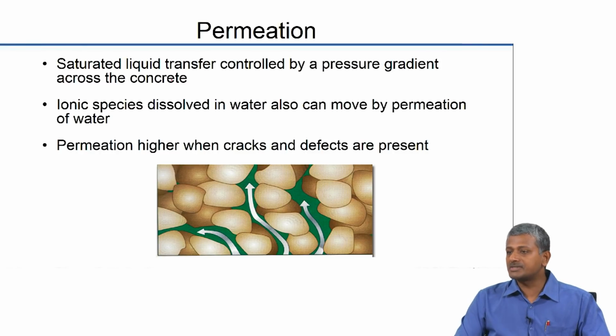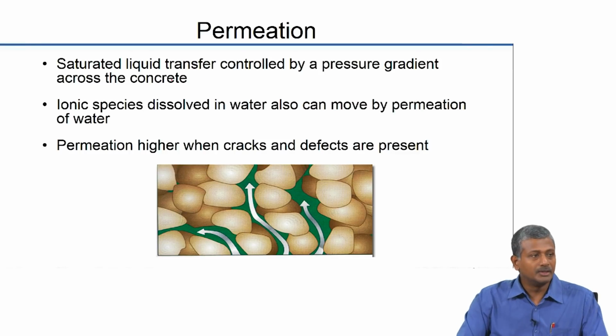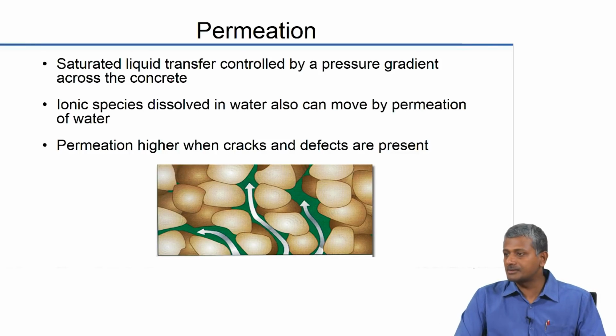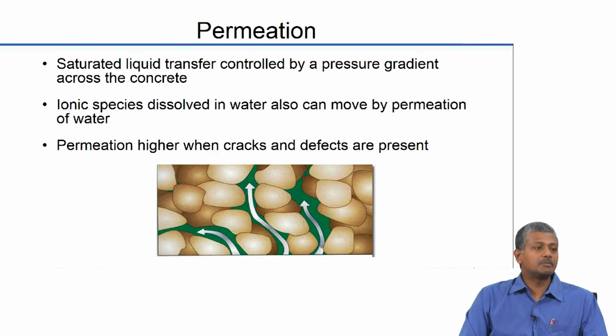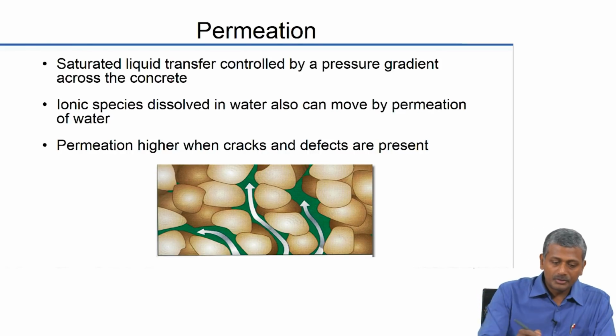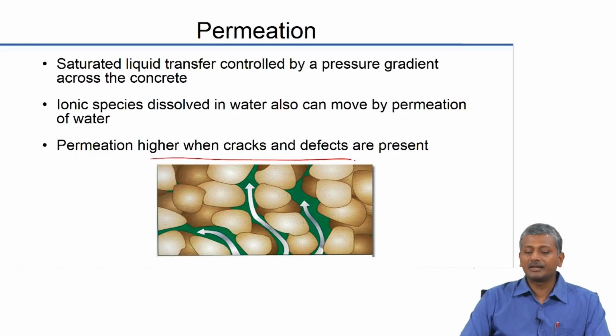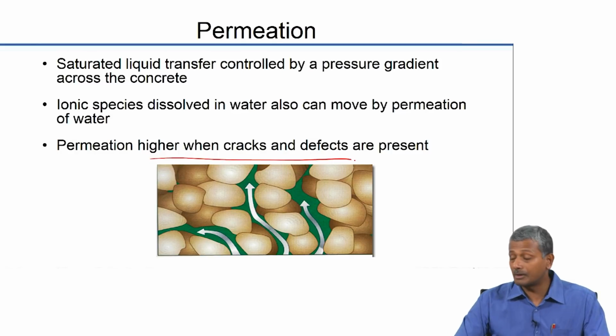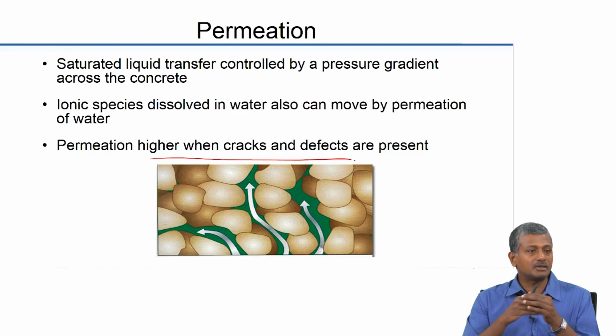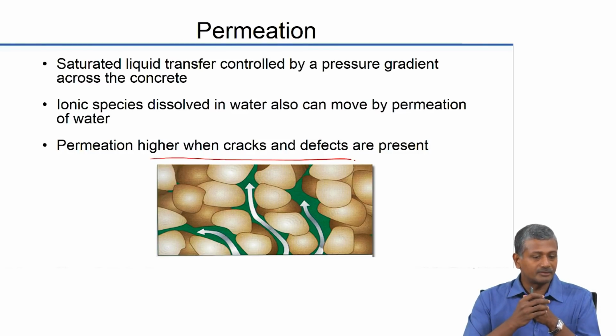Now, the ionic species that are dissolved in water can also move because of permeation. Ionic species do not always have to move because of diffusion. They can also be carried by the water into the concrete. For example, sulfates, which are dissolved in the groundwater, can get carried by water into the concrete because of permeability. So, permeation obviously is higher when there are cracks and defects present in the concrete. Water does not have to permeate through regions of porosity, it can permeate directly through the cracks and defects in the concrete.